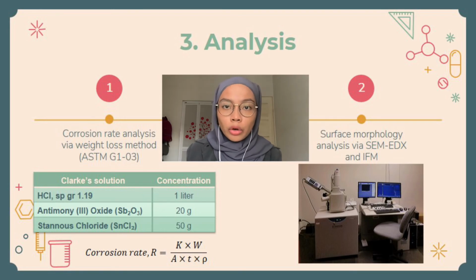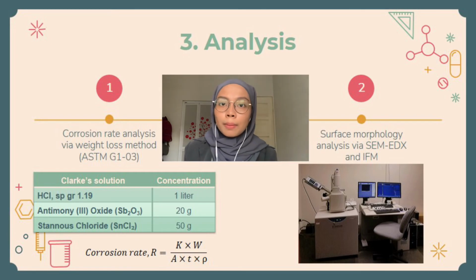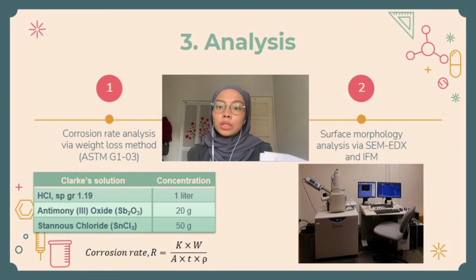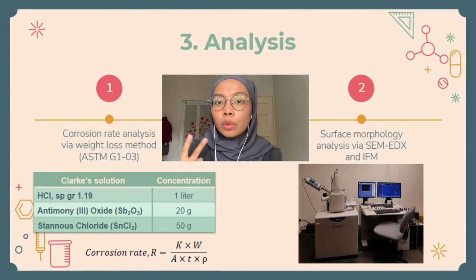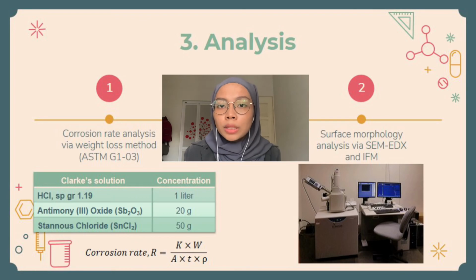Measurements were taken of the weight of the coupon prior to running the experiment and at the end of the experiment with FeCO3 scale present on the surface, and after the corrosion product was removed by using Clark solution. So the concentrations of Clark solutions are 1 liter of hydrochloric acid, 20 gram of antimony oxide, and 50 gram of stannous chloride. So from the weight loss measurement method, the corrosion rate can be calculated by using the equation of R equals to Kw over A T density.